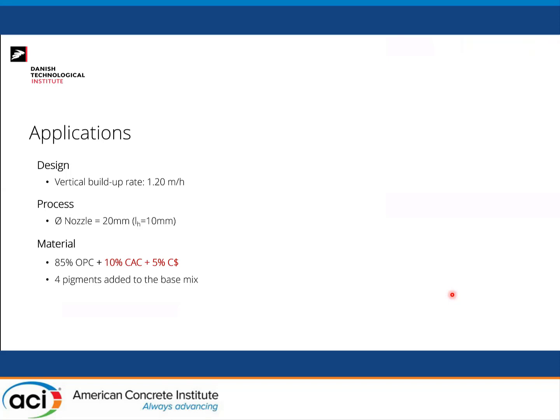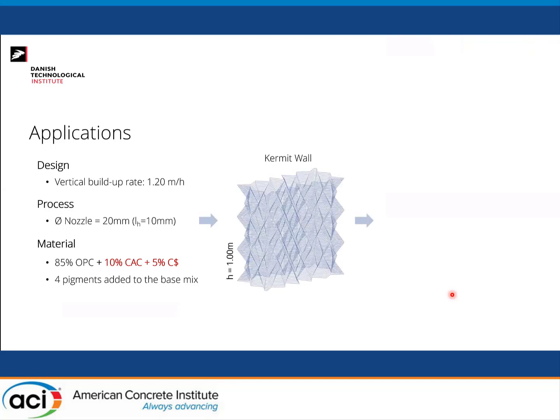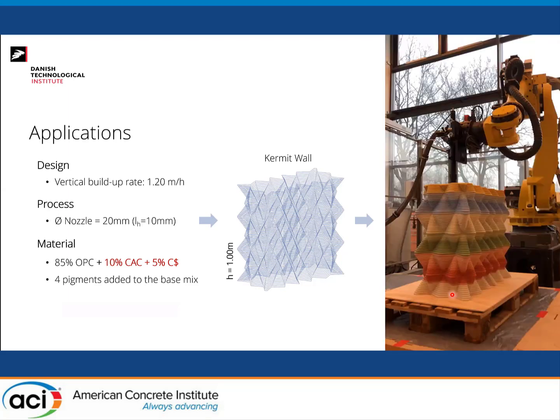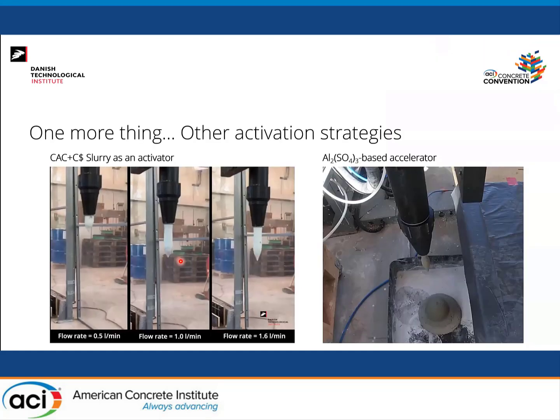And then likewise, we reduced a bit the vertical build-up rate, and I'm already in the application sections. We came up with some different ideas of how to test. We wanted to test which kind of overhangs the material could or could not take, plus there are some other architectural aspects. I don't have to go into details here, but we could perform now at 1.2 meters per hour, and we could accomplish a successful print. I said we went down to 1.2. We identified that anything above 1.7 meters per hour would mean the failure of a mix that has this amount of calcium aluminate cement and calcium sulfate as an activation.